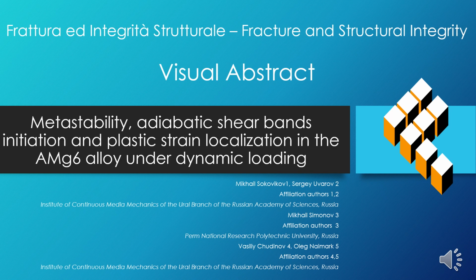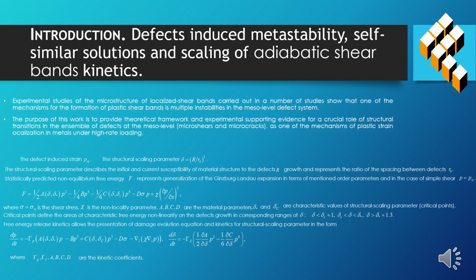Experimental studies of the microstructure of localized shear bands carried out in a number of studies show that one of the mechanisms for the formation of plastic shear bands is multiple instabilities in the meso-level defect system. The purpose of this work is to provide theoretical framework and experimental supporting evidence for a crucial role of structural transitions in the ensemble of defects at the meso-level, microshears and microcracks, as one of the mechanisms of plastic strain localization in metals under high-rate loading.